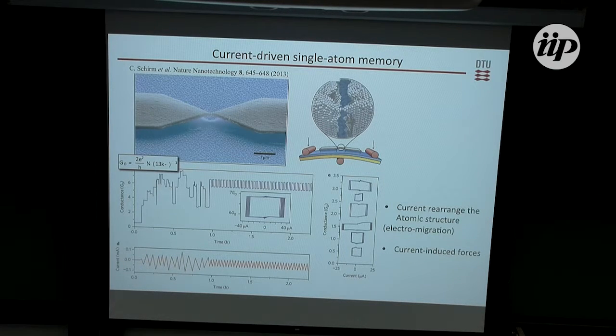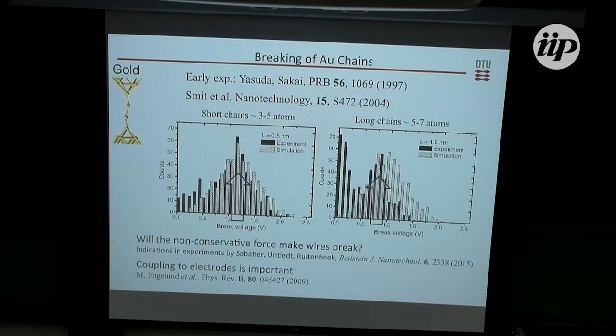So it's like they're flushing current and more current, and then something happens, and then they flush it the other way. And in this way, they can actually make this configuration here toggle between two or more metastable states. So the current can sort of kick the atoms from one to another. So this could be one example of these current-induced forces where the direction is very important.